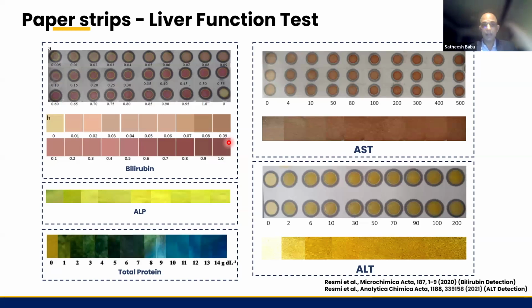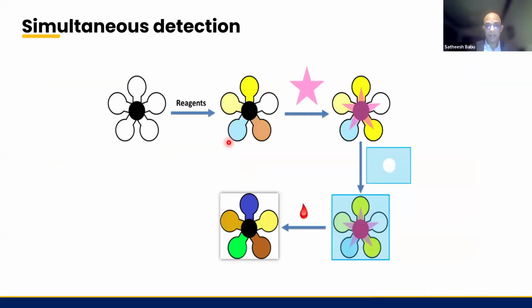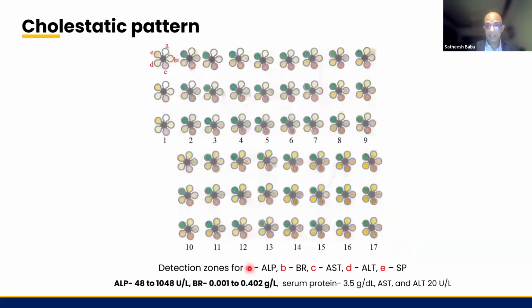Once we have developed all these five analytes separately, we tried integrating them into a simple stamp-sized paper strip, wherein I have 5 wells, and introduced all the reagents for them. Then a plasma separation membrane was placed. Then this is actually a polymer backing to give mechanical support. Then once we introduce the sample, we see the color change, right? Then we have tested all possible ways.